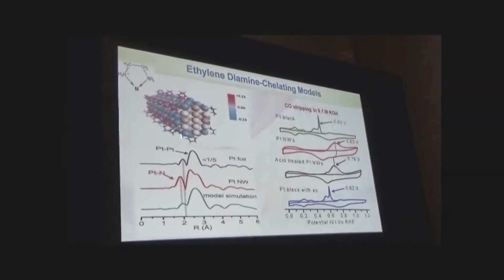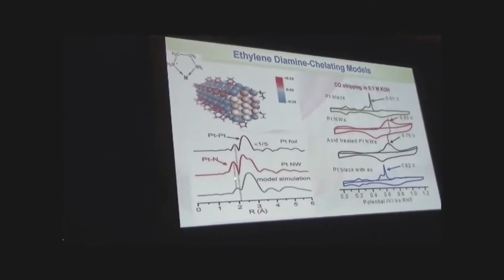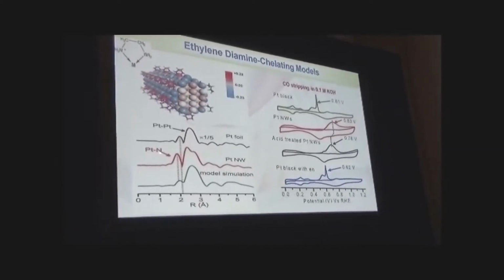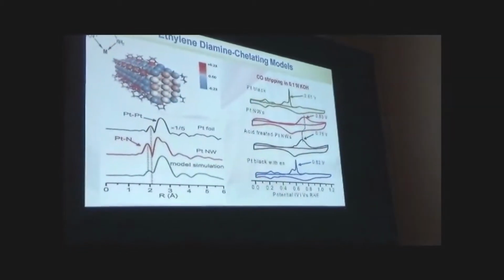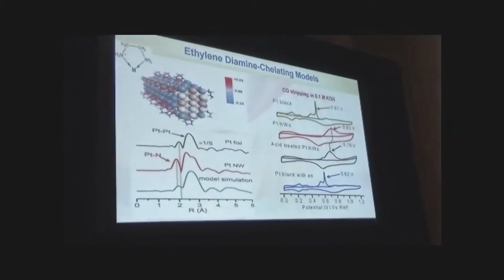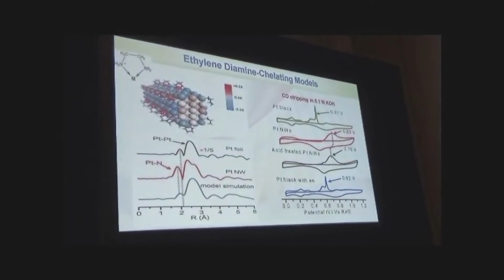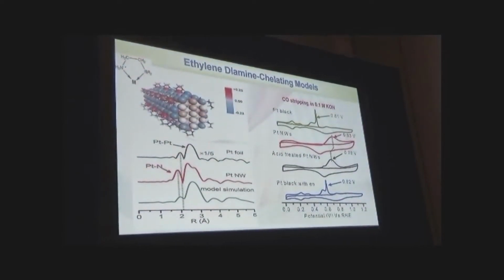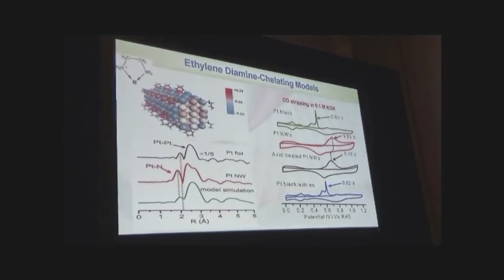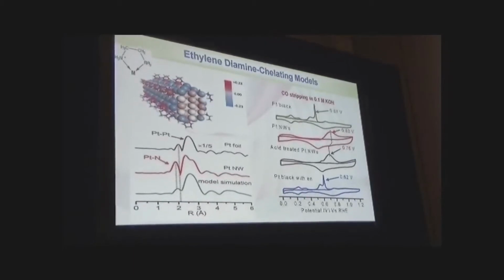So here we have an example. Here we have Pt. This is the Pt-N bond here. And we also use CO stripping. You can see that this is the CO stripping, the peak is shifted from here to here. So this demonstrates the electronic effect. We can modify the electron state of the Pt nanowire.